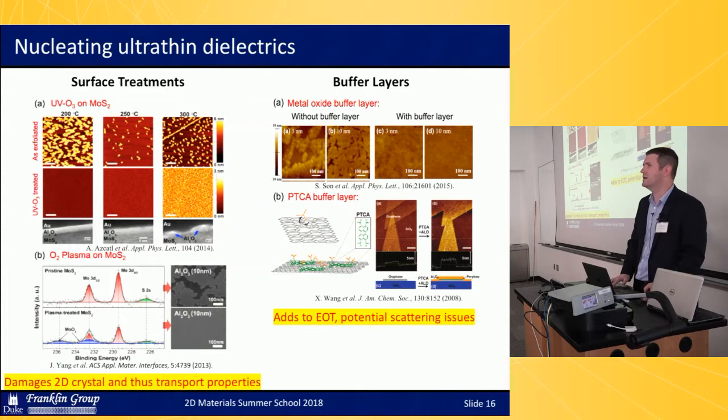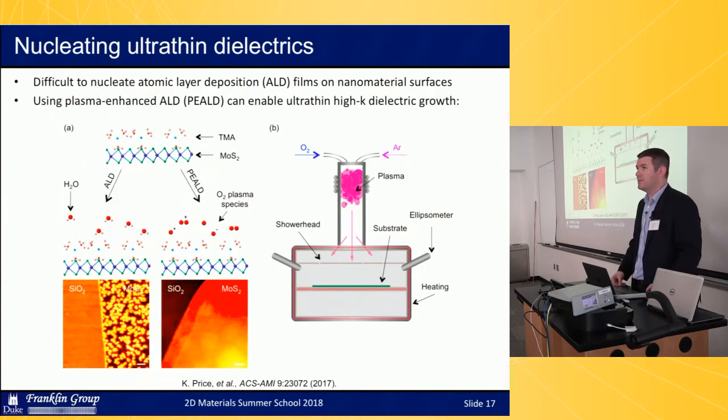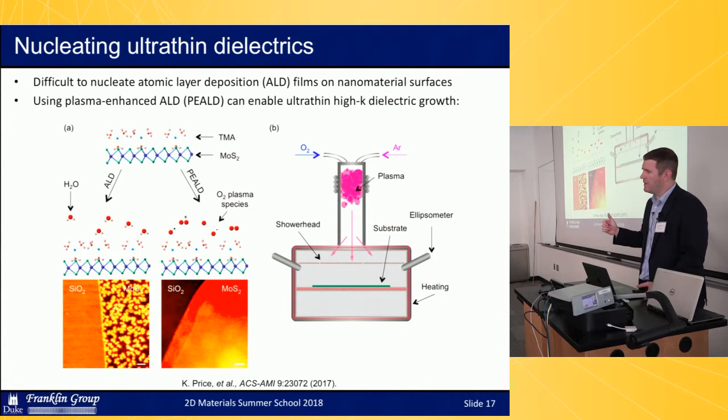The one that I'll show you that we've developed in my lab is a very straightforward one, because most ALD reactors have this capability built into them, and that is using a plasma-enhanced step for the oxidant pulse rather than just a thermal ALD process step. First of all, I want to be clear about the impact of using a plasma in this type of ALD approach. If you look at the system schematic on the right-hand side of the slide, the plasma itself is a remote plasma, a plasma that's upstream from the actual ALD reaction chamber.